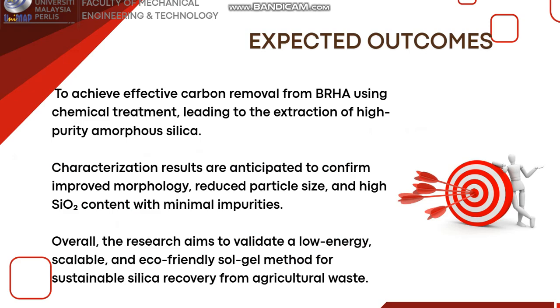The outcome that is expected is to achieve effective carbon removal from BRHA, resulting in high purity amorphous silica. Characterization should show improved morphology, smaller particle size, and high silicon oxide content. Overall, the process aims to demonstrate a low energy, eco-friendly, and scalable method for silica recovery.